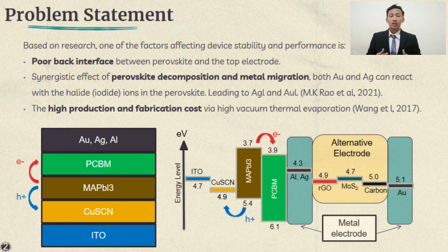Despite the exciting performance, perovskite solar cells encounter stability problems that make them degrade faster, hence restricting bulk production to meet industrial needs. Based on research, one of the factors affecting the stability is the poor back interface between perovskite and top electrode. Currently, the state-of-the-art top electrodes of perovskite solar cells are usually noble metals such as gold, silver or aluminium. However, due to the synergistic effect of perovskite decomposition and metal migration, both Au and Ag can react with halide ions in the perovskite, leading to the formation of AgI and AuI. Other than that, the high production cost is also one of its limitations, because they are normally fabricated by rigorous processing of high vacuum thermal evaporation in a vacuum chamber.